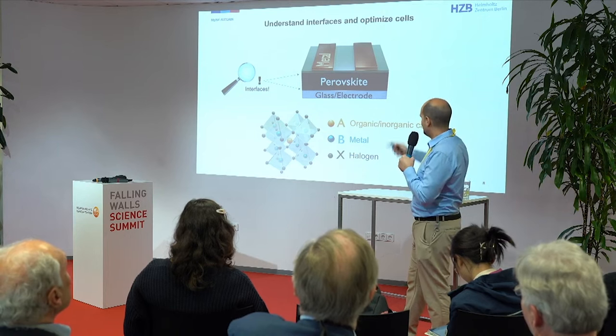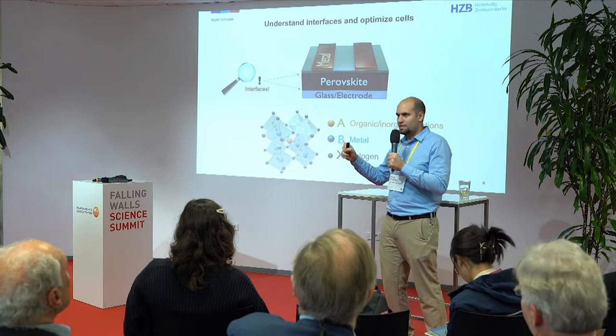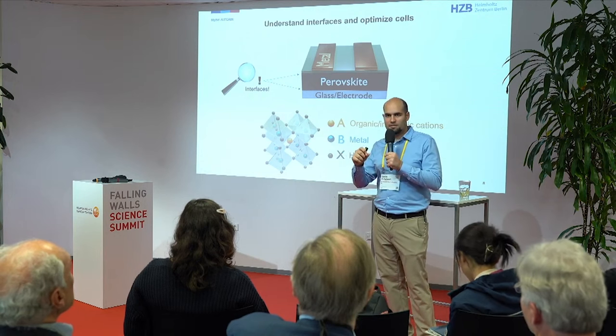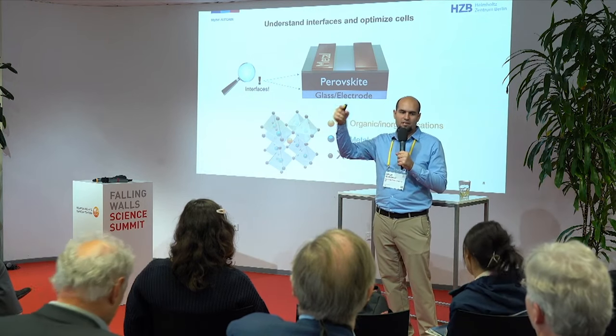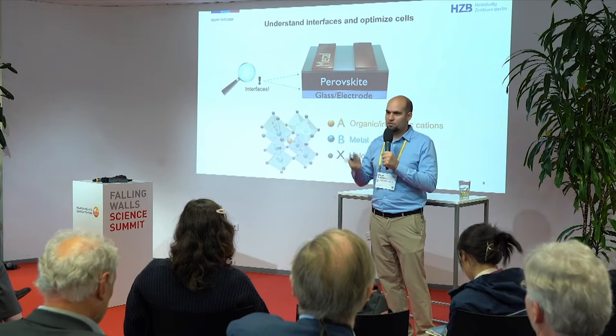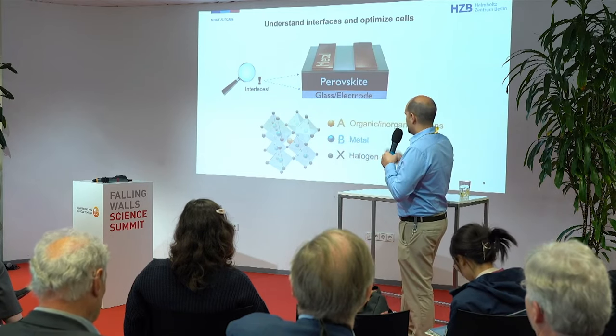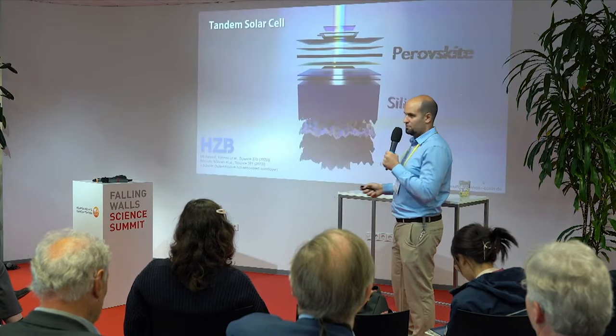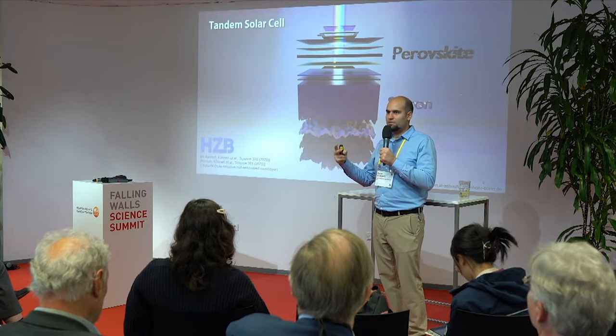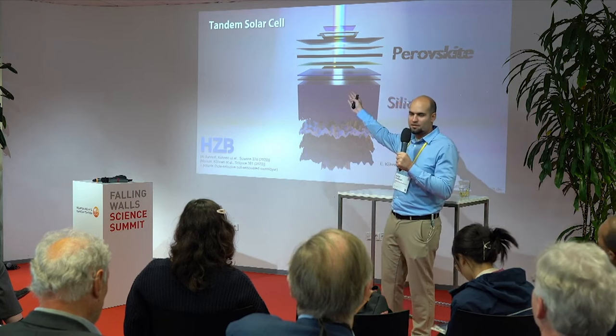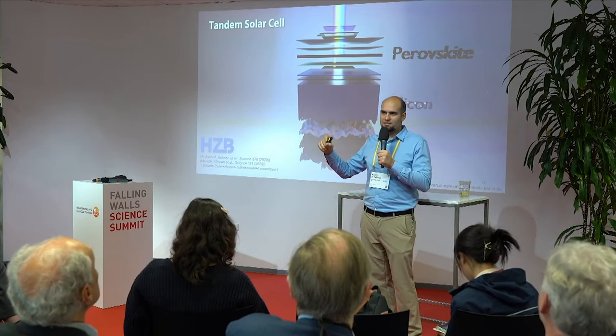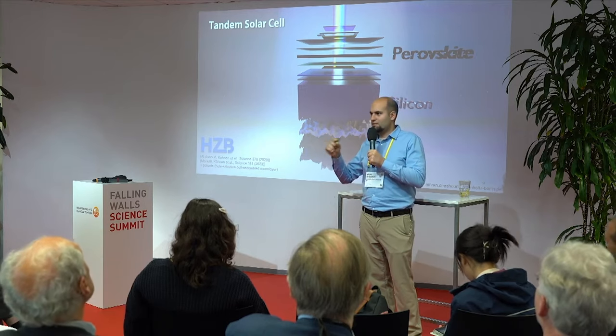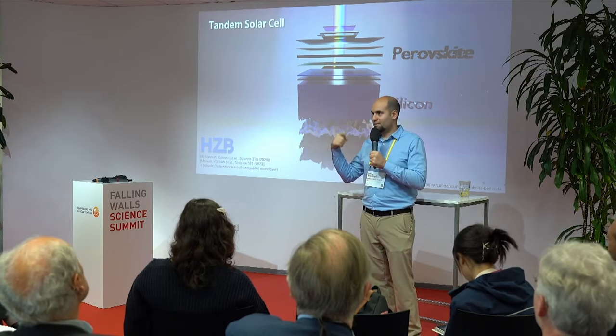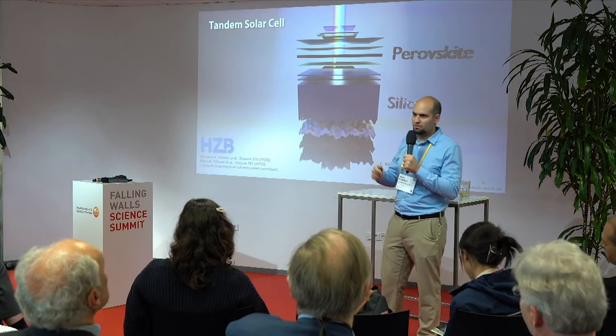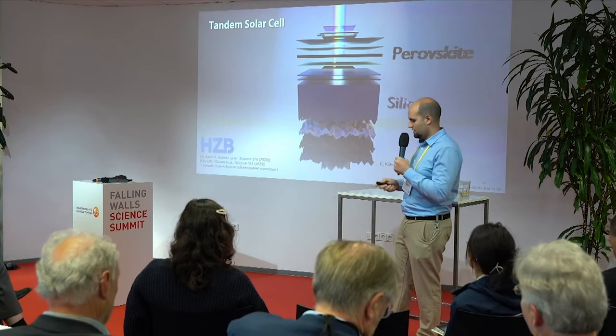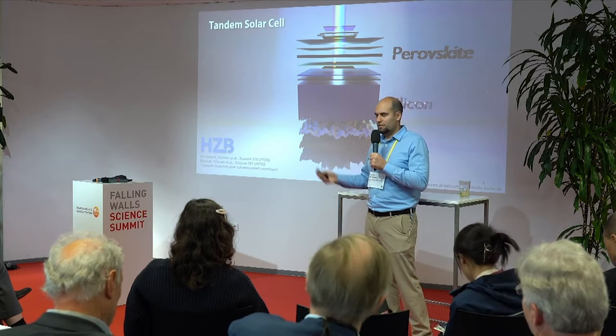So we then try to understand this and master how to optimize the interfaces with especially organic molecules that are compatible to both the inorganic electrodes and the hybrid inorganic-organic perovskite material. You can do this in single-junction solar cells, but the real challenge is to do this in the tandem solar cell, right? Because you don't only have two interfaces, but a lot of layers in this tandem stack, and you need to optimize all of these interfaces and also optically optimize the thicknesses of the layers, but also electrically optimize to reduce non-radiative recombination, namely, at the interfaces, by energetic alignment, but also defect trap density.